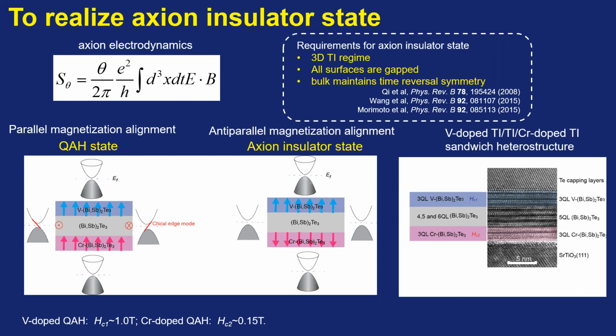The first condition is the TI film needs to be in the 3D regime, and all the surface of this TI must be gapped, and the bulk of the TI needs to keep the time reversal symmetry. So, we know that we have realized the quantum anomalous Hall effect in the chromium doped and vanadium doped system, and these two systems have different TC.